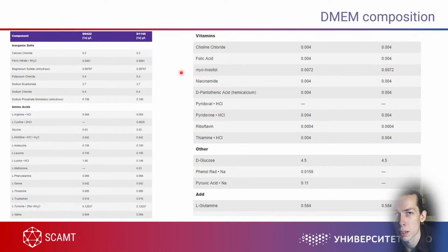These nanoparticles can be completely non-toxic, but because they adsorb some part of the nutrients from culture media, the cells died just because of depletion of nutrients in culture media. And, well, it's quite a complicated matter to discuss.